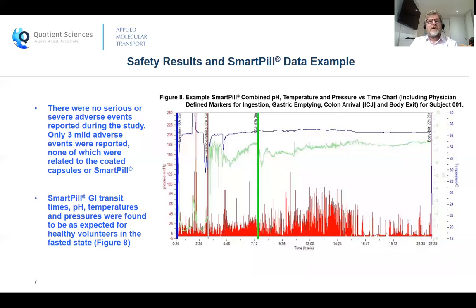On a volunteer safety note, only 3 mild adverse events were reported by our principal investigator during the study, and none of these were related to the coated test capsules or the smart pill. Figure 8 on this slide shows a typical example of smart pill data we generated, in this case for subject 001. The red profile is pressure, blue is temperature, and green is pH data, all against time on the horizontal axis. The thick grey and green vertical lines are the key times of gastric emptying and colon arrival.